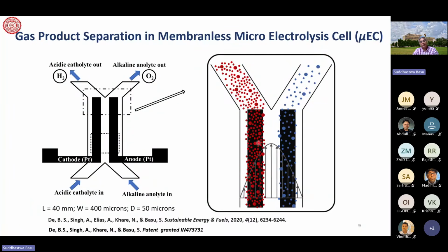And here we are showing that if you can accomplish the hydrogen evolution reaction and oxygen evolution reaction at the respective cathode and anode, they will travel through the stream and they will remain separated. No mixing will take place, because they are moving with the stream along the streamline, without any physical separation or membrane, just because of the interface of the two fluids, which will be maintained because of the laminar flow, and there will be no intermixing, and you will get the hydrogen coming out, which is the red color, and oxygen coming out with the blue color along with the stream, and the hydrogen evolution reaction will take place at the cathode, and the oxygen evolution reaction will take place at the anode, as shown here.